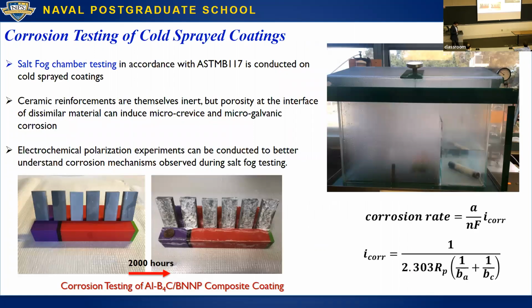And so we did the hardness testing. It showed improvement. We did corrosion testing using a salt fog chamber, and we haven't done too much of the polarization type experiments yet. But the Navy is very interested in salt fog chamber testing because it's one of the most realistic environments, short of actually putting something out on a boat.